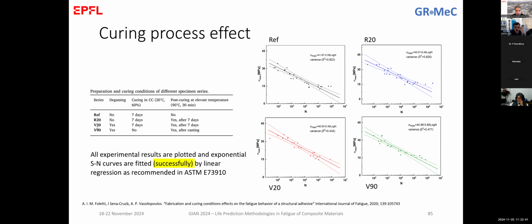Then we had the V. V means that we had degassing for the specimens that were 7 days left in the lab at 20 degrees, so V20. And then after 7 days, we had the degassing. And then we have this V90 that was mixed, degassed, and without any time in the lab was post-cured directly at 90 degrees after casting. So we did tests for these specimens, quasi-static and fatigue.